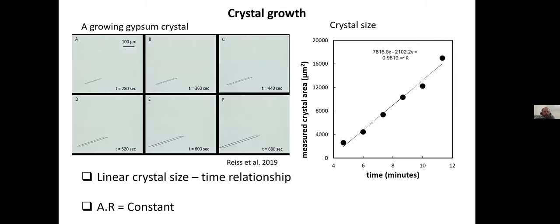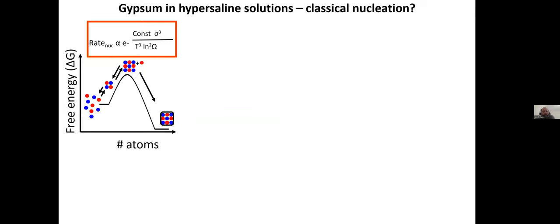I also looked at specific single crystals growing from solution. There's one image here, and a single crystal also shows a linear size with time growth pattern. And another thing, the aspect ratio of the crystals during this growth of a single crystal remains constant, which tells me that the ratio of growth rates of different faces is constant. Now, these observations I've shown you, it's all observations, no calculations or modeling, are somewhat problematic. And I'll explain why.